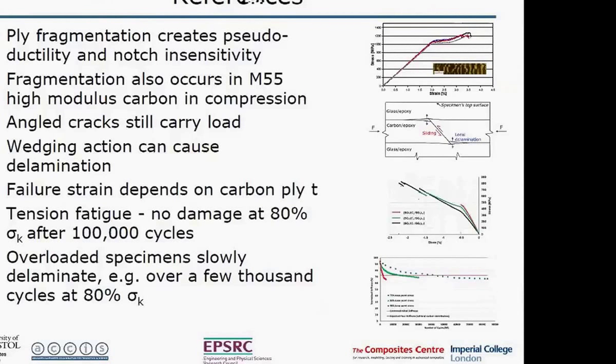So the carbon fibers are not very rate sensitive. The glass fibers show some rate sensitivity. So for glass-carbon there may be some effect, but under the rates we looked at, you don't see much of a rate effect on these hybrids. The rate effect also affects the G2C, so it may affect the boundary between the different failure modes. But generally speaking, to a limited extent, we've done high rate tests and we don't see very much. In contrast, the angle ply composites, which I didn't really have time to talk about this morning, rely on the sliding action, which is down to the shear behavior. Those ones do show a rate effect.